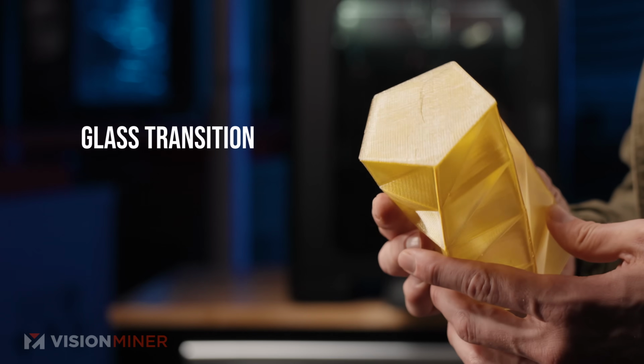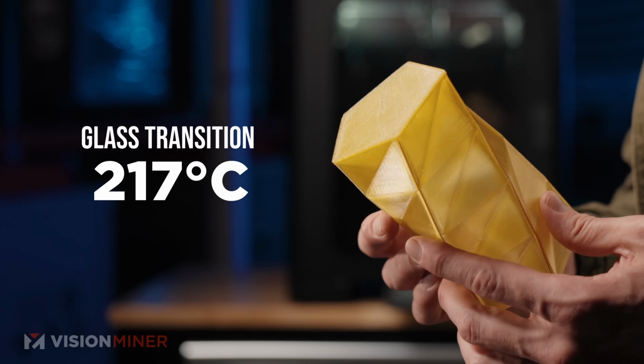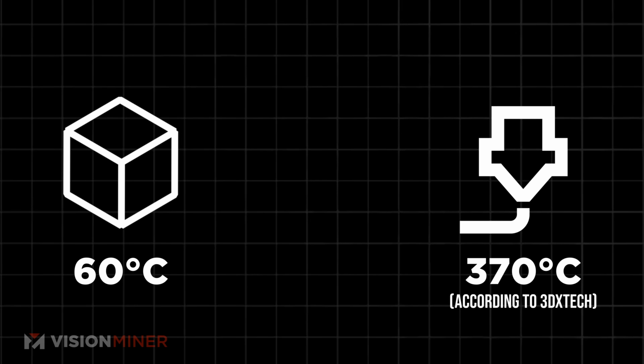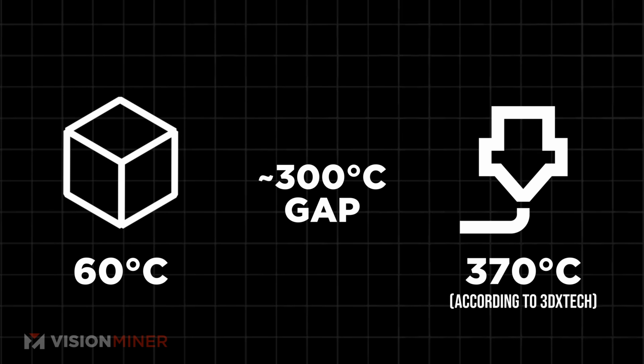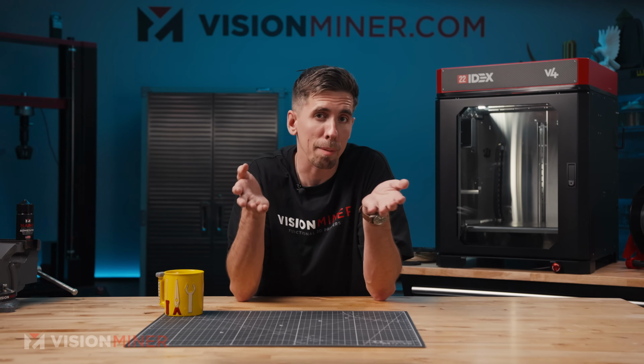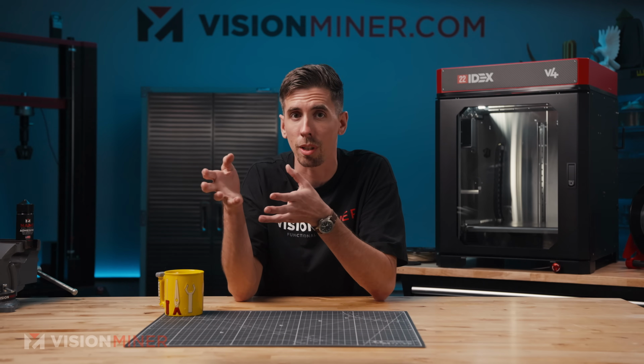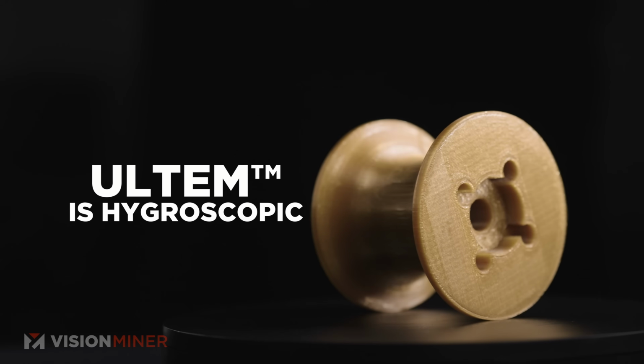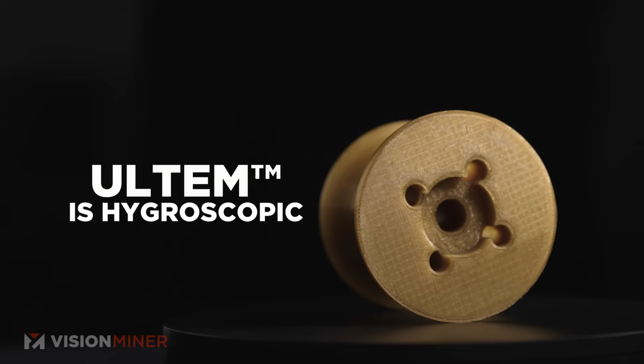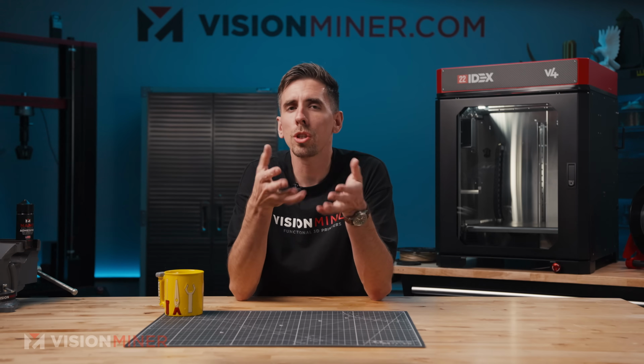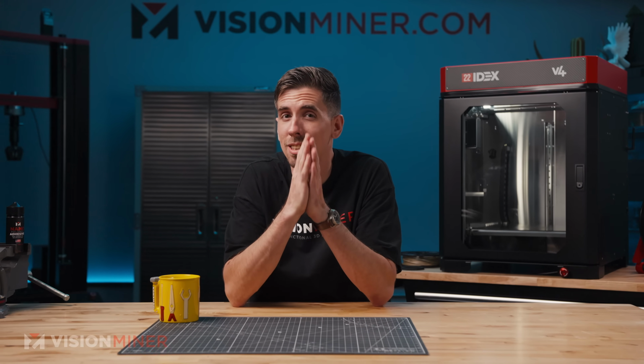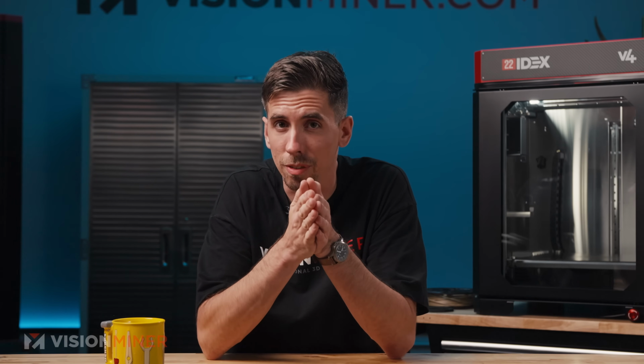Secondly, its glass transition is 217 Celsius. So if your chamber's at 60, you've got nearly a 300-degree gap between fresh extrusion and cold part. And that is basically the gap where parts tear themselves apart. Thirdly, ULTEM is hygroscopic. That's HYGRO. It basically means that it pulls moisture out of the air, and it does so very aggressively. This is something we see like literally every day.